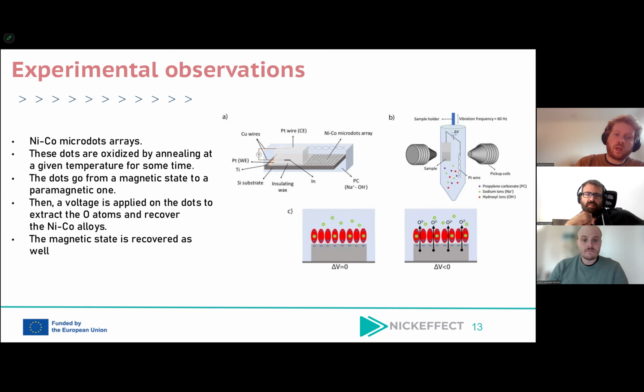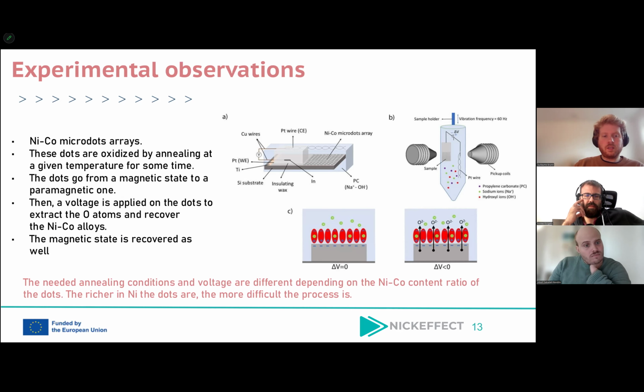And after that, they were applying a voltage to the dots to remove the oxygen atoms and recover the nickel cobalt alloys, and then also recover the magnetic state. And the thing that they wanted to understand was why the annealing conditions, so the temperature and the voltage, were different depending on the nickel cobalt ratio, the content ratio in the dots. So if there were more nickel in the dots, then they needed a larger temperature to anneal and go to the paramagnetic state. And they also needed a larger voltage to remove the oxygen atoms and recover the magnetic state.